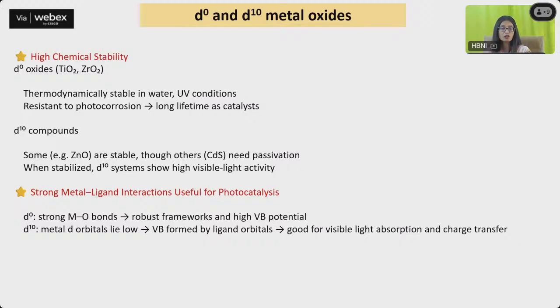So these are the kinds of materials which we saw in the previous slide. Then you have very high metal ligand interactions, which is again useful for photocatalysis. These d0 systems form very strong metal oxygen bonds, so they have robust frameworks and a very high valence band potential. For d10, again, the metal d orbitals lie low, so the valence band is formed by the ligand orbitals. This is very good for visible light absorption and for charge transfer. So that is the reason why d0 and d10 metal oxides find a lot of application as photocatalyst materials.